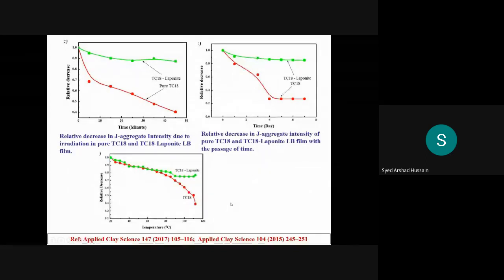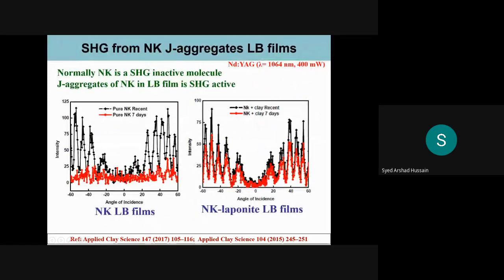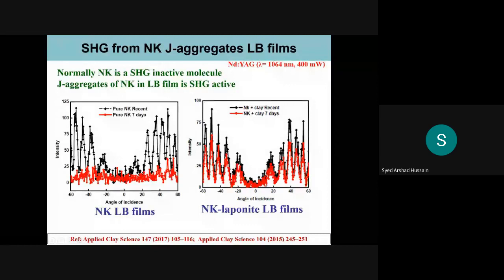But when we prepared the system in the presence of clay, one can see the stability enhances. And you can see here the SHG signal intensity; the black one is from the freshly prepared films, these thiocyanine J aggregate films in the LB system. Then after 7 days, we measured the same SHG intensity, and you can see it decreases. But when we prepared the system in the presence of clay, you can see the black one, freshly prepared. Then after 7 days, you see the intensity decrease is very small compared to this one. So here, the clay helps us enhance the mechanical stability of the J aggregate in LB film. And we have seen that it remains almost stable even after months.